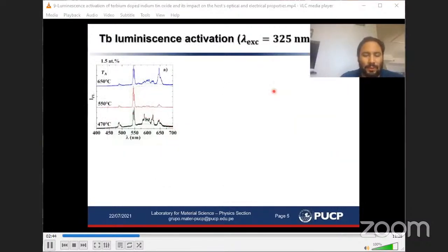We were able to obtain the luminescence from the terbium ions embedded in this host by post-deposition thermal treatments and under this excitation wavelength. Here I'm showing you the luminescence spectra for 3 different annealing temperatures of a sample with 1.5 atomic percent of terbium. We are able to identify the typical electronic transitions related to the terbium ions. And interestingly, we see that the 5D4 to 7F2 transition increases in intensity for this annealing temperature. This is quite an unexpected behavior.